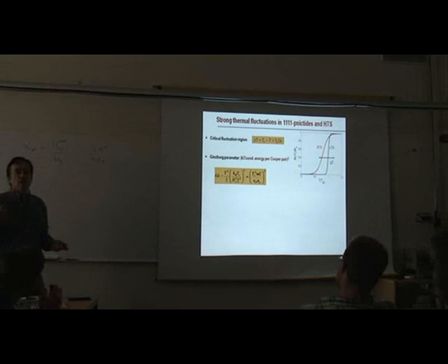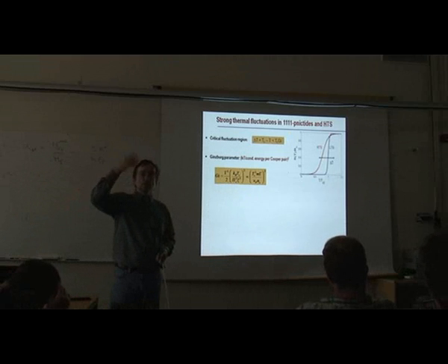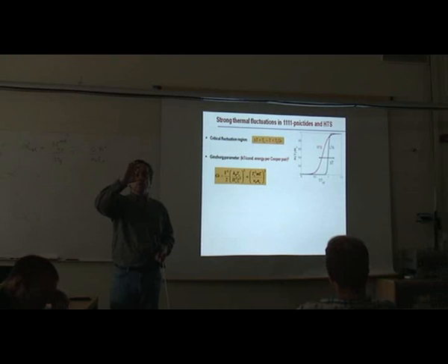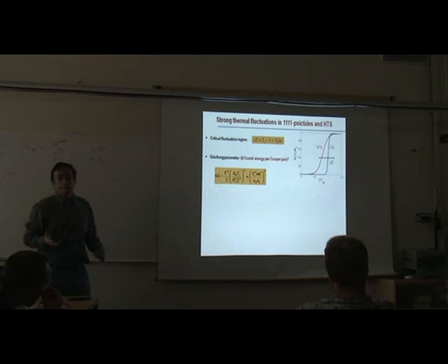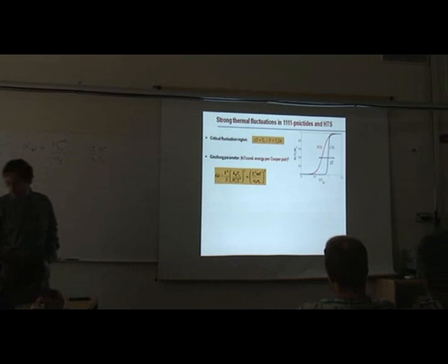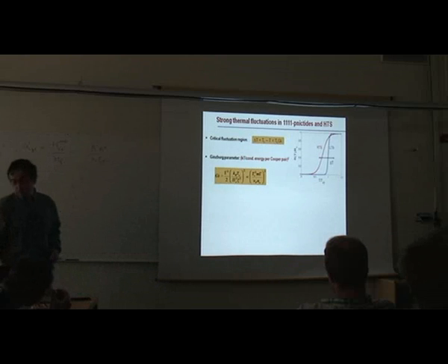So basically what you do, if you calculate the correction to the specific heat in the first Gaussian approximation, the fluctuation correction, and then say this delta Tc should be of the order of the jump at Tc in the Landau theory. That's how you get that. That's how it was actually calculated. But qualitatively, it's simply this kT divided by the condensation energy squared.